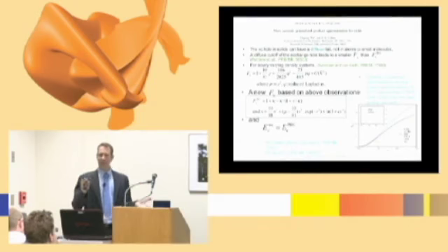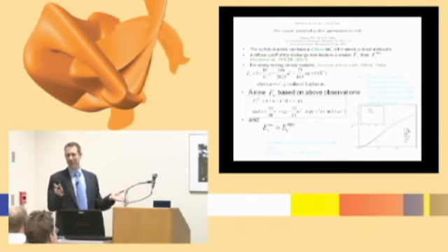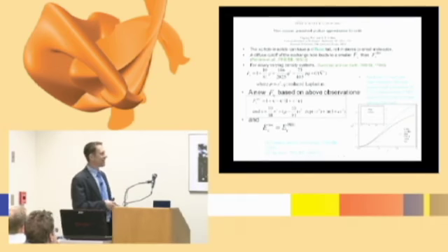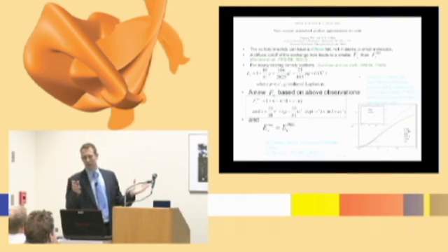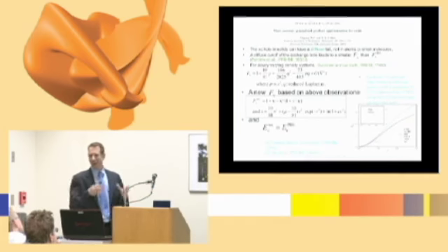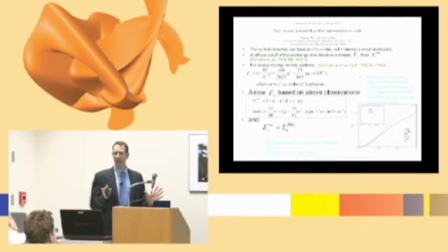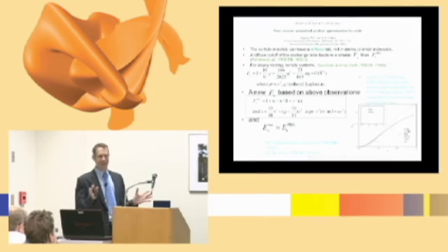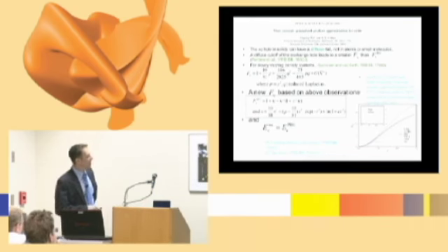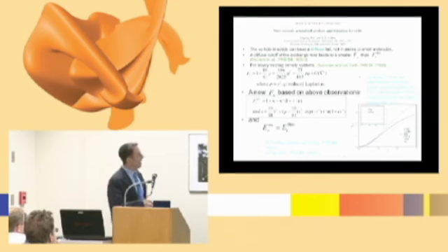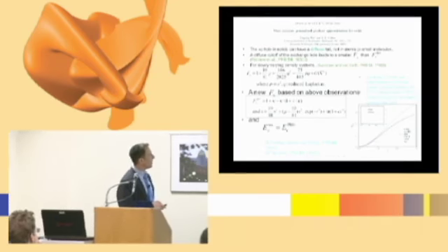I showed you how things were right within a few percent, but lead titanate was really a bad actor, and it was just awful. The C over A was coming out far too big, and the volume was off by 20%. We thought for weeks that there was a bug in our code, but there wasn't. So we wanted to come up with something that worked better.